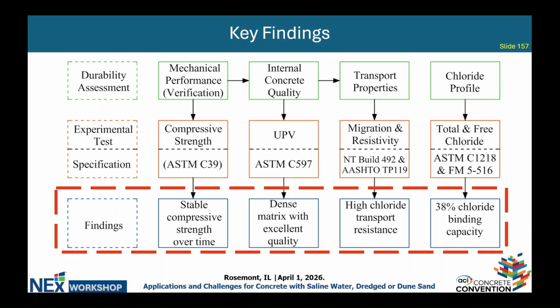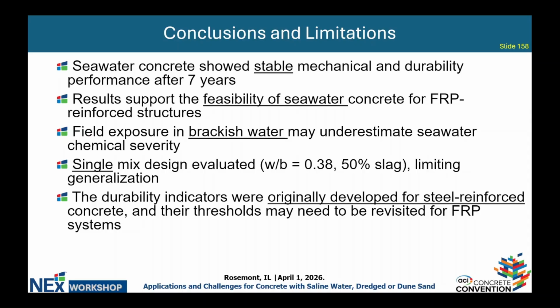The key thing here is that our durability assessment indicators consistently show durable performance of seawater concrete exposed to real marine exposure, starting from the compressive strength that showed a stable structural performance, as well as the excellent internal concrete quality, ending up with the indirect indicators using the transport properties, as well as the 38% chloride binding capacity. Now, the main conclusion of our study is that this system is durable when exposed to real marine exposure, and it also highlights the feasibility of using seawater concrete with FRP reinforced concrete structures.